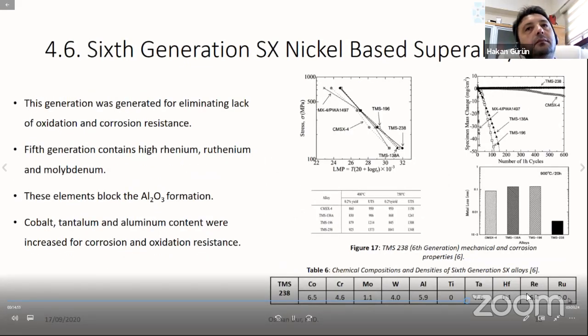For eliminating the corrosion bad feature, a sixth generation was developed. Today, sixth generation alternative material studies are continuing. Fifth generation contains high rhenium, ruthenium, and molybdenum. These elements block the aluminum oxide formation at the surface and decrease the corrosion and oxidation performance. Cobalt, tantalum, and aluminum content were increased for corrosion and oxidation resistance. As you see in the figure, TMS-238, sixth generation material, is better for strength and corrosion properties when compared with